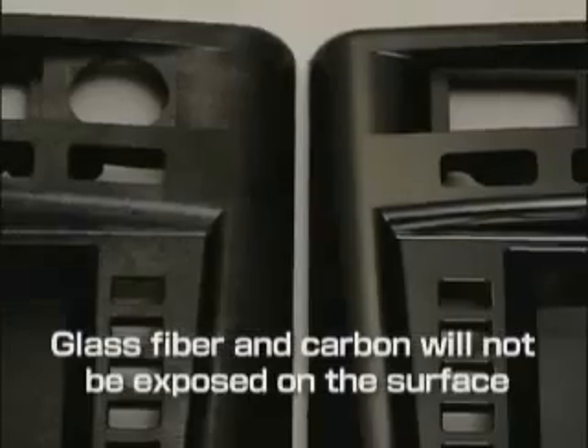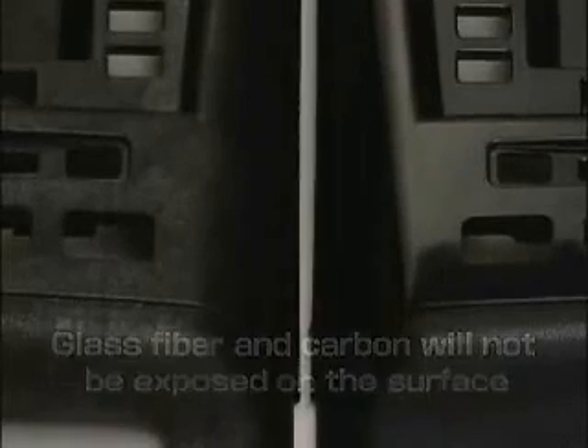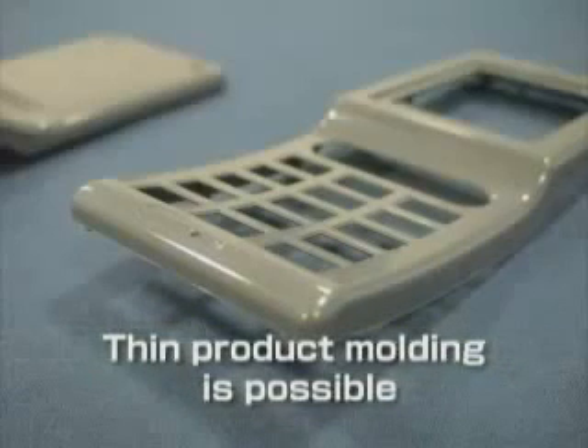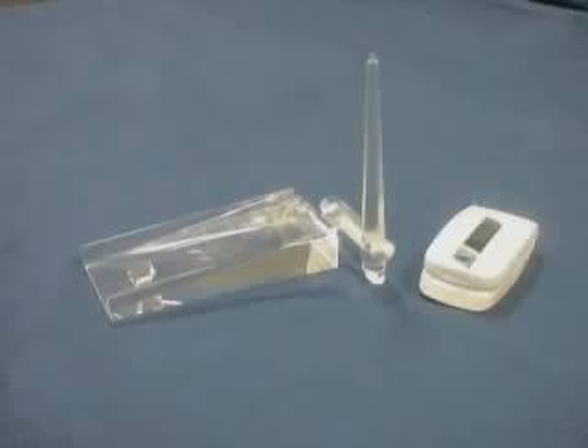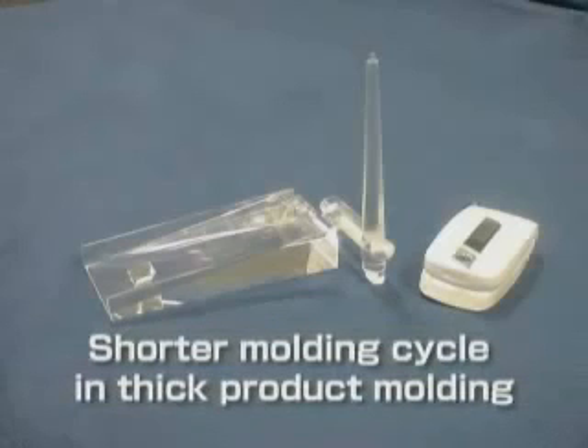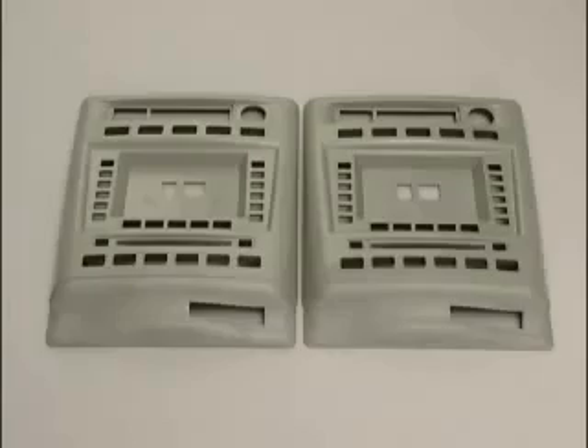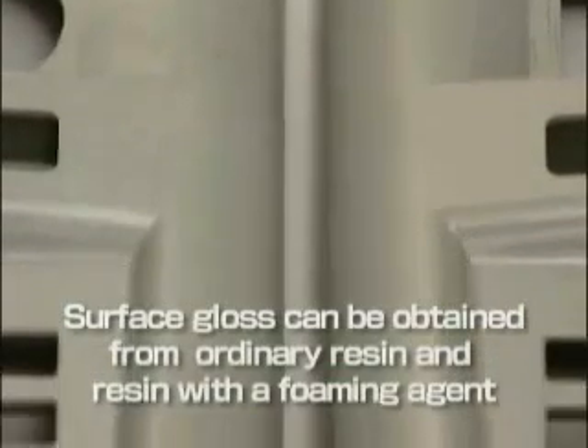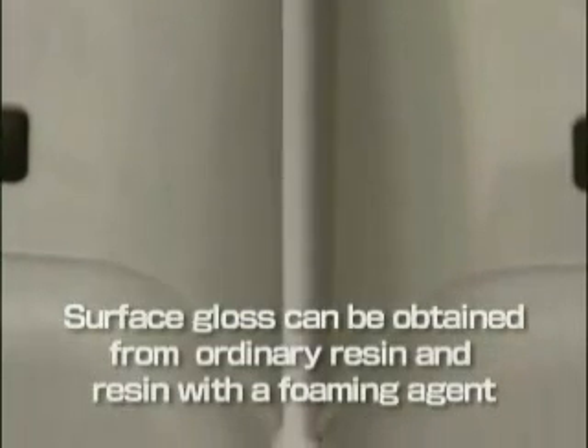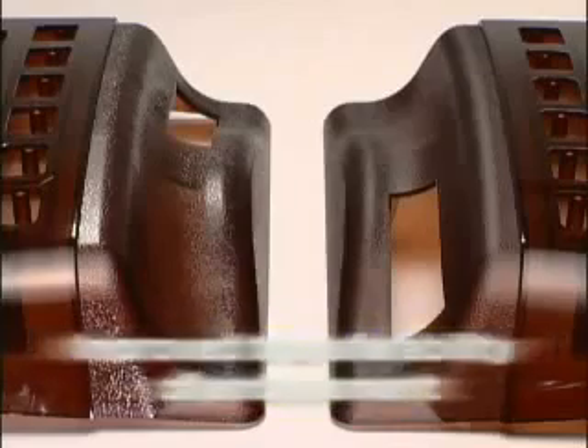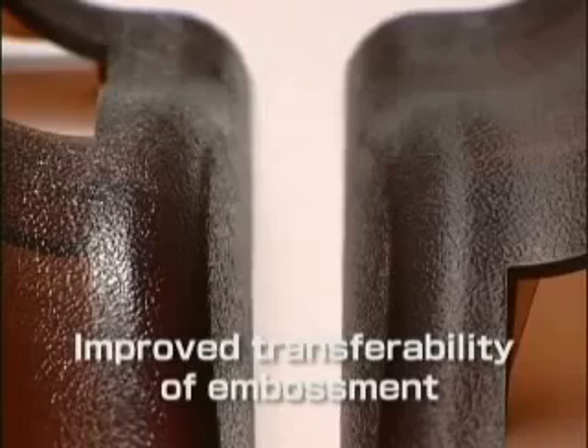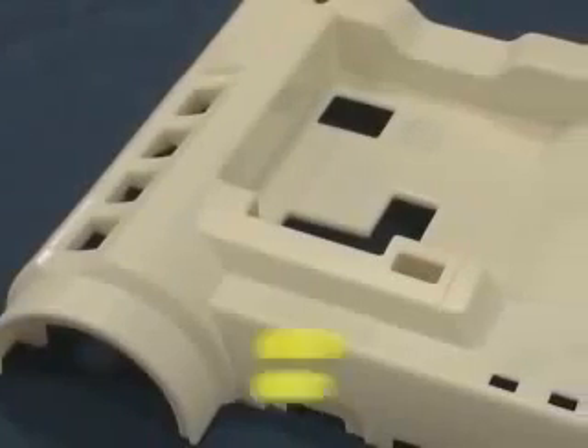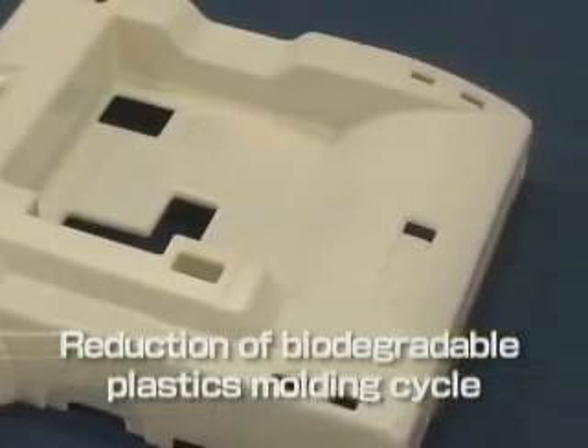Plastic molding using heating and cooling and the 3D weldless mold provide a number of other merits. Glass fiber and carbon will not be surface exposed, and a clean surface gloss is achieved. Fluidity of resin increases, making thin product molding possible. Even in thick product molding, the molding cycle can be considerably shortened. Surface gloss can be obtained from ordinary resin and resin with a foaming agent. Moreover, transferability of embossment increases. It is also effective for reduction of the molding cycle of biodegradable plastics.